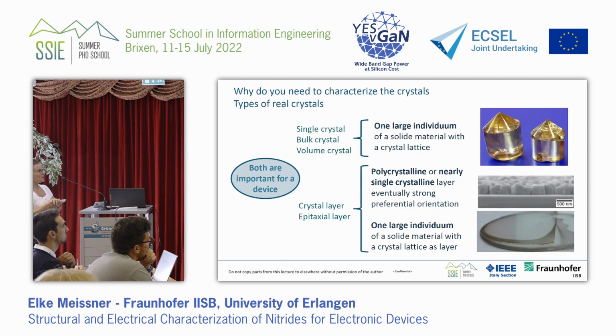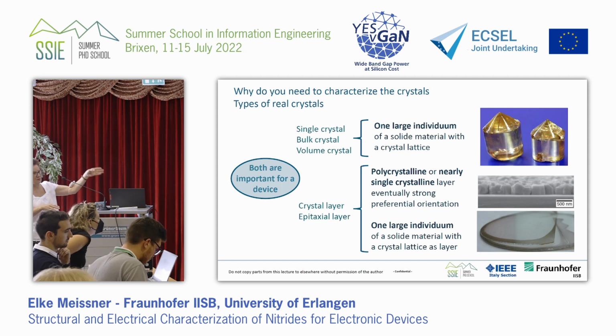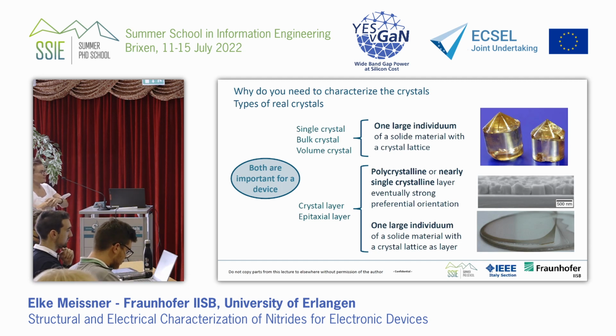And then we say, okay, a single crystal. Now we need to characterize the crystals. So this is the starting point. How good will the epitaxial layer be if we regard the perfection of the crystal? Because the crystal perfection will be a fingerprint that is taken over to the epitaxy. So we have single crystals, bulk crystals, volume crystals, which are all the same. Boule is sometimes a name for it. This considers a large individual, a big piece of a semiconductor with one lattice all over this big piece. Then we have crystalline layers, which can be polycrystalline with strong preferred orientation, I would say. Or we have a very large but very, very thin single individual, which is an epitaxial layer. All these we have to consider because this is all important for the final device.